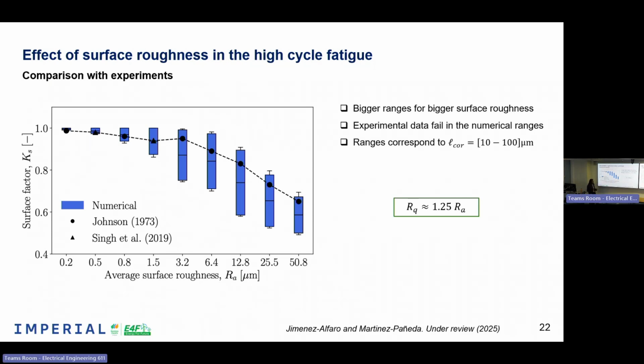So first of all, as you observe, when we increase the average surface roughness, the ranges are bigger. This is because the presence of the correlation length and also the stochastic is more important. Here in black, we have represented several experimental data. We have represented the estimate given by Johnson in the 70s, that was this first graphic I have shown to you in the introduction, and also the experiments done by Singh et al. in 2019. And as you can see, the experiments fall into the ranges. Moreover, as soon as the average surface roughness is growing, the experiment seems to be closer to the upper bound. So that means that the typical correlation length of those profiles maybe is bigger.